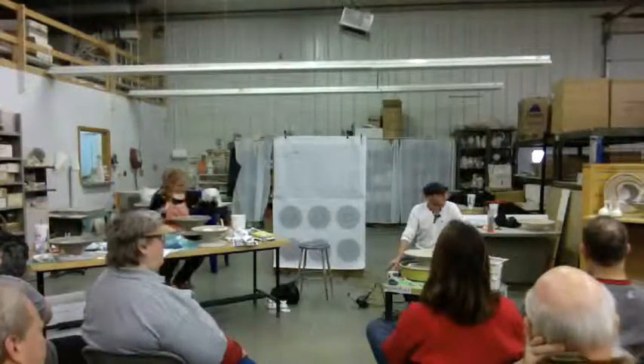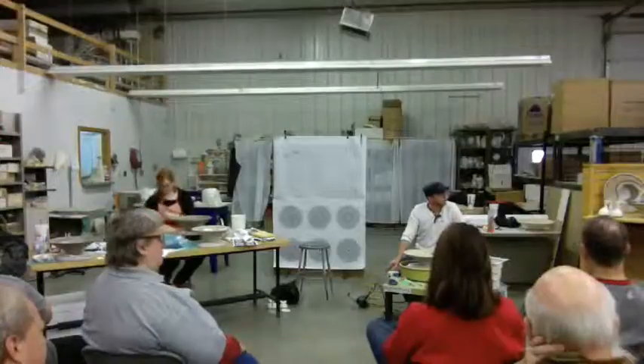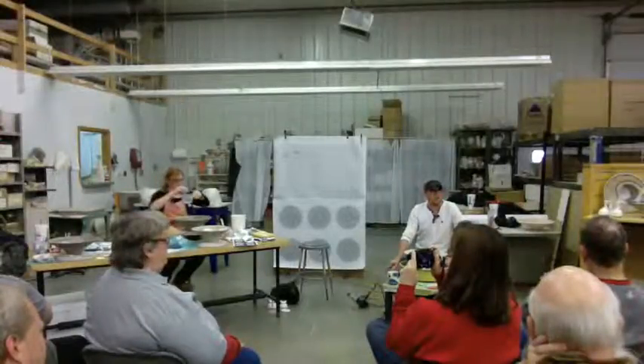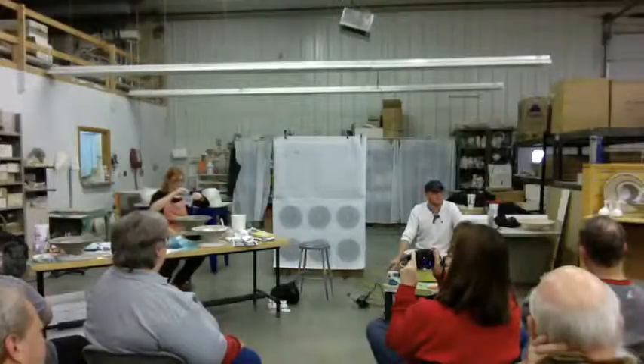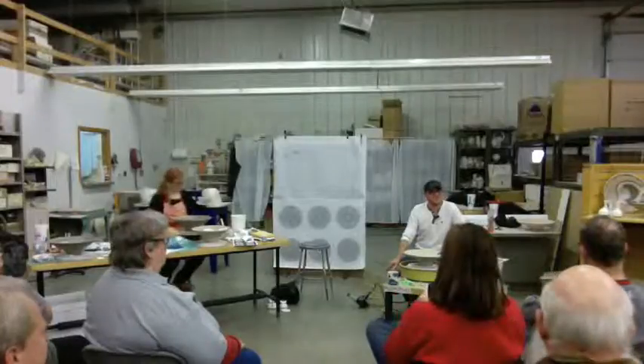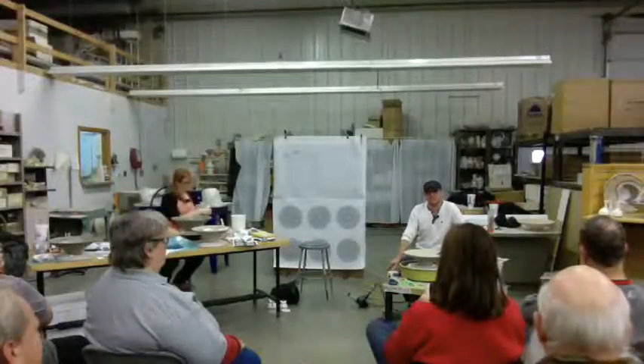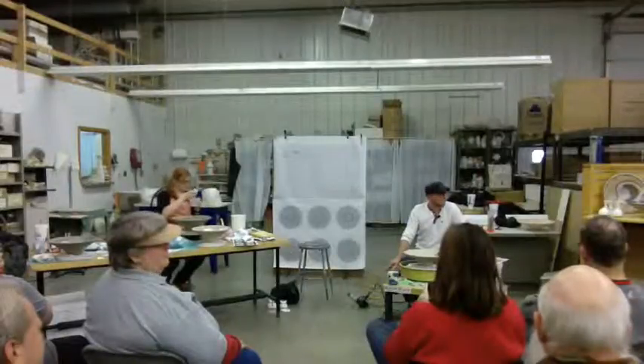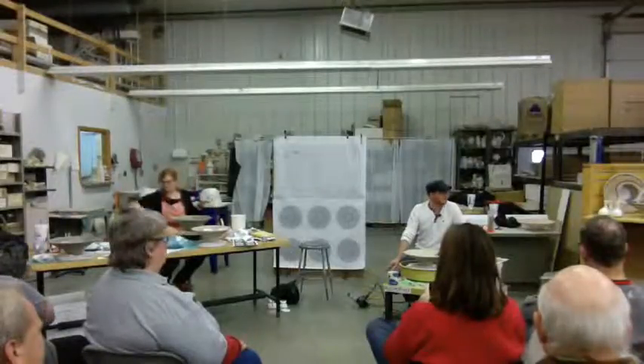Because there's little tricks you can do. Like if you were to put stannous chloride over the white, it'd pearl it to make it opalescent. Silver nitrate over white crackle turns it gold. But those are all light-sensitive hazardous chemicals. But I would say ceramics is all hazardous.